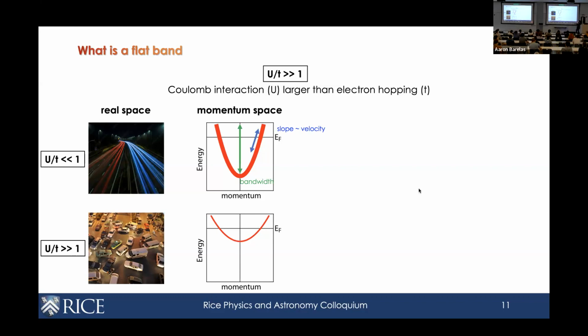So if you go to this regime where the interaction is so strong that things are slowing down, what are you going to see from ARPES spectra or band dispersions? You're going to see the bandwidth being reduced, the slope being reduced. Slowly this band is going to be squeezed and flattened against the Fermi level. Eventually, when you reach the point where there's no more motion, where everything is local, that means in momentum space this becomes a completely flat thing, and that is called a flat band. This is a regime where the Coulomb interaction is much stronger than the hopping of the electrons. Okay, so intuitively, this is the picture.